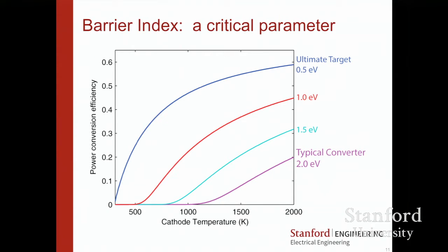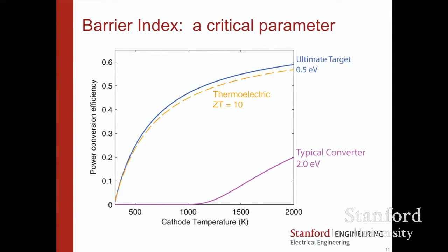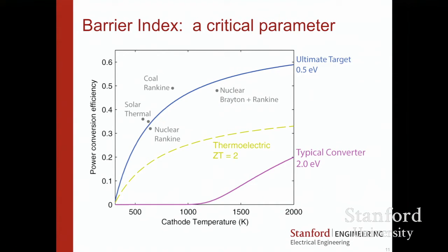So this is adapted from work by Hatsopoulos and Gyftopoulos, a couple of obviously Greek engineering profs at MIT in the 70s. And thermoelectrics are much more studied, with huge investment in thermoelectrics. For those that know thermoelectrics, a ZT of 10 is outrageous, right? People sweat bullets to get a ZT of like 2 or less. And also the materials in thermoelectrics have great difficulty at very high temperatures. So the vacuum gap and these very simple materials tend to mean that thermionics gets into a position of potentially higher efficiency if you have the high heat source. And so ultimately you're competitive with these well-developed technologies, or an assist to them in some cases.